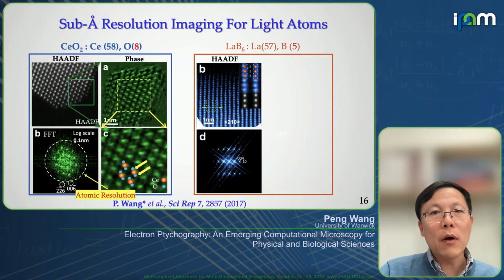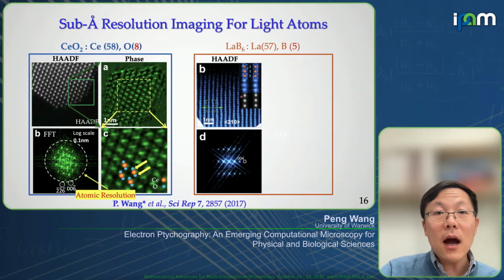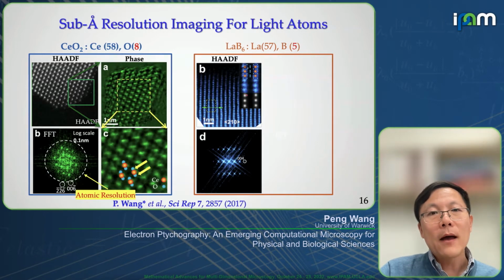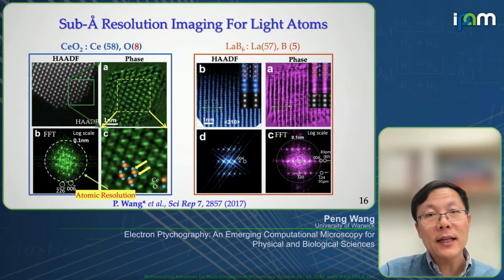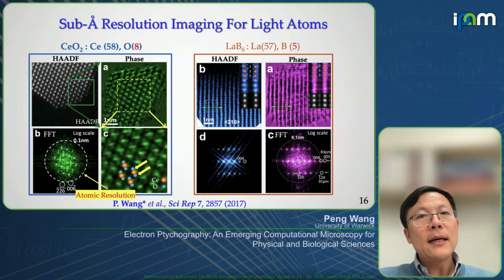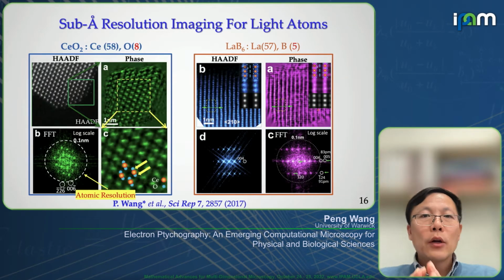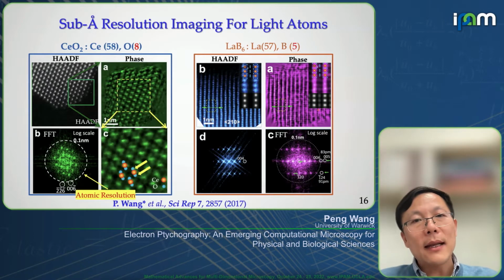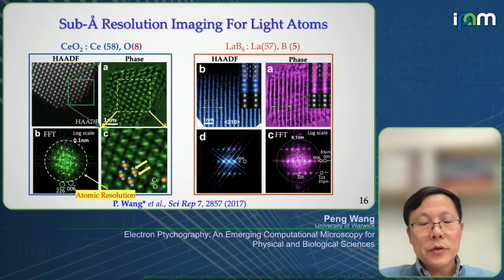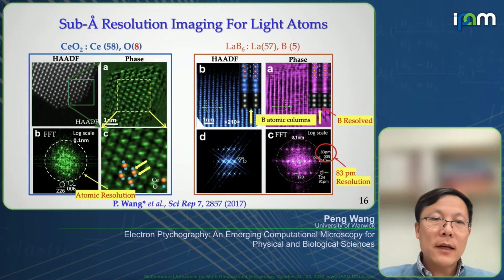And we further prove this using lanthanum hexaboride, the LaB6 crystal, where boron is 5 and lanthanum is 57. As you can see in the HAADF, the lattice is really empty. All the bright spots correspond to lanthanum columns. Even in the simulation, without any noise, you still can't see any boron atomic column. But when you use ptychography phase reconstruction, you start to see the additional columns between the lanthanum. Therefore, this phase imaging is really sensitive to light atoms and allows you to observe light atoms in a heavy atom crystal. The resolution also achieves 83 picometers.